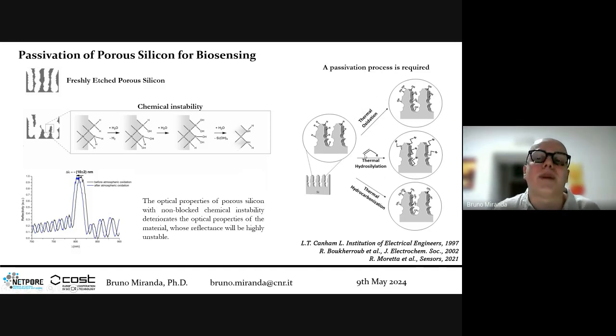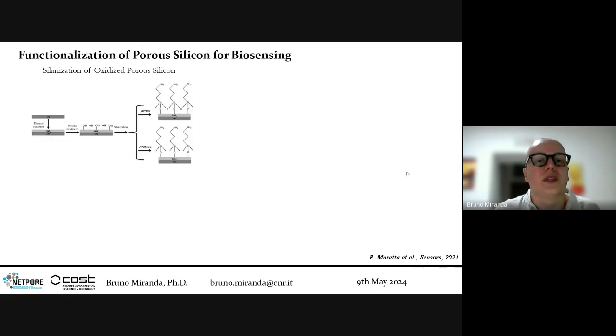Or you can have other strategies such as hydrosilylation and hydrocarbonization, in which you substitute the very unstable Si-H groups with Si-C, silicon carbide, so silicon carbon bonds that are much more stable and also offer the possibility to link other molecules on top. So this is a typical functionalization strategy.